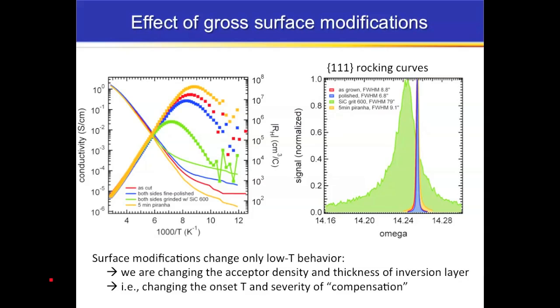What this shows us is that only the low temperature data is being affected by these surface modifications. All the high temperature data is hardly affected at all. If we assume or believe that this low temperature data is dominated by the surface, then this makes sense. It's consistent that the surface is what we're changing when we modify it in this way, and that we're changing in some fashion the acceptor density, perhaps the thickness of the inversion layer, and that's leading to this low temperature behavior change.